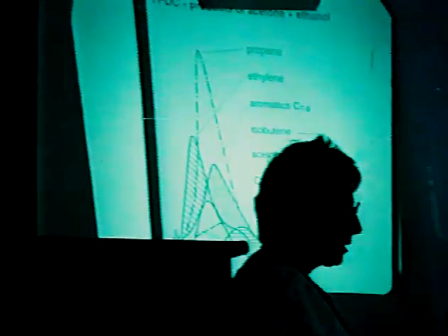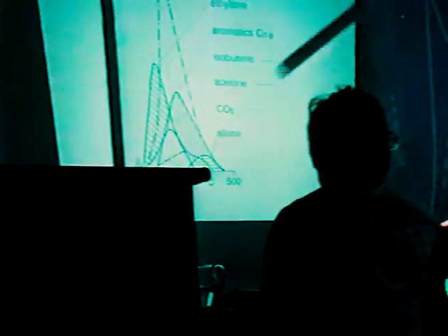And that is our further evidence that in the reaction of methanol with acetone surface species and ethanol with acetone surface species, the presence of ammonia doesn't suppress formation of aromatics, in contrast to the reaction of acetone alone or of methanol alone or of acetone with acetone surface species.